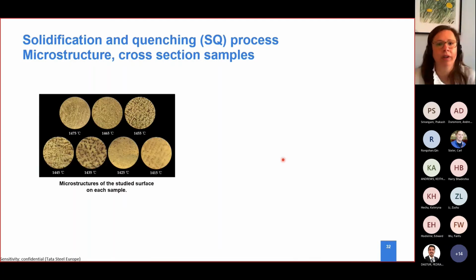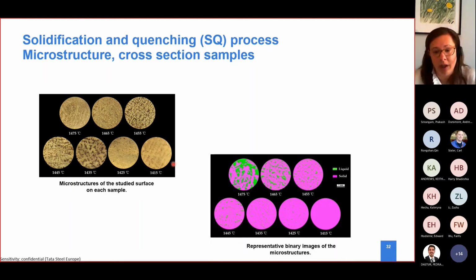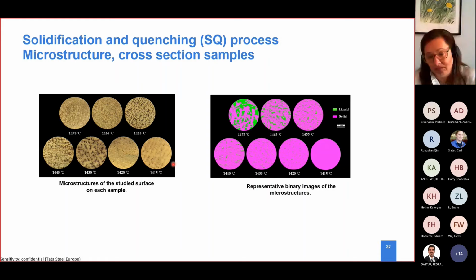How does it look? If we take out one sample and quench it at different stages, we have different microstructures. With a simple image analysis, we could say the areas in between those dendrites we could relate to a liquid phase that has been very fast solidified, compared with the solid phase that was solidifying before this quenching. We can follow the liquid phase fraction from this high temperature to this low temperature for this particular steel.